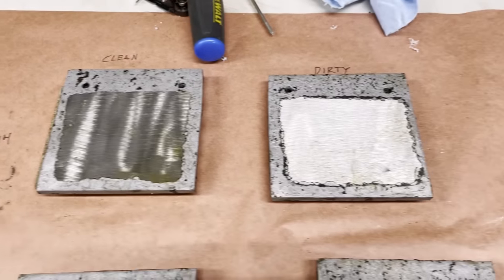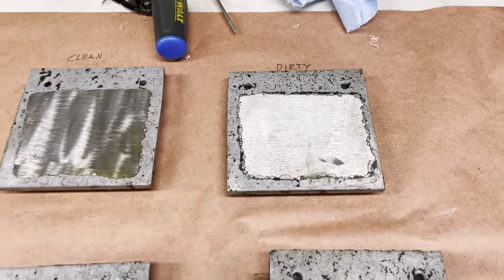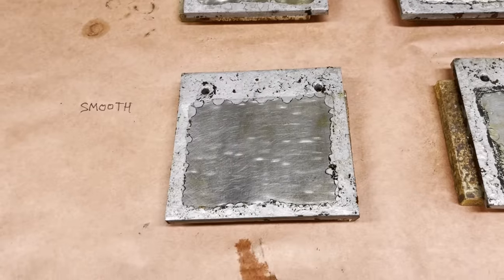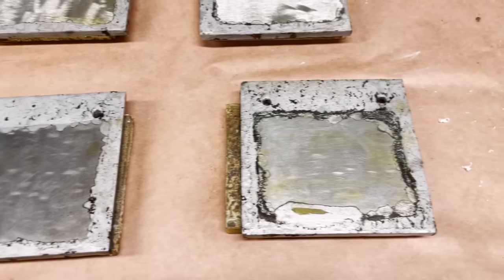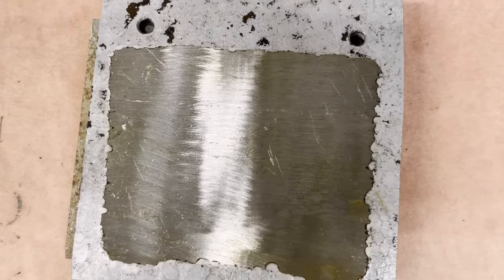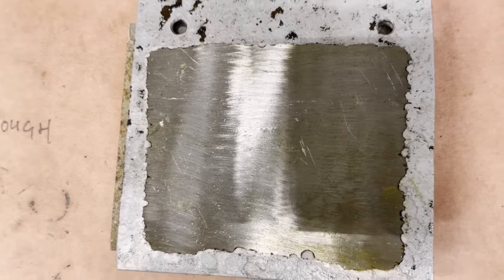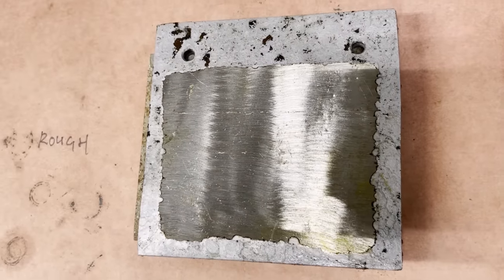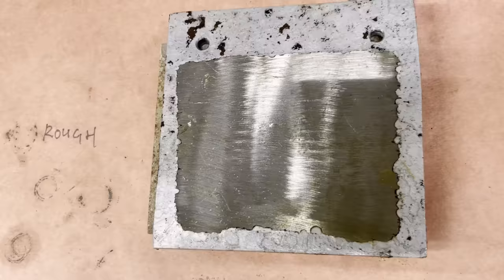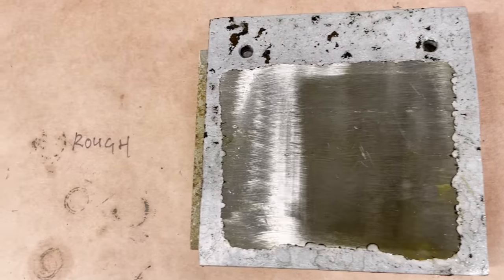At first glance, the coating appears to have protected all the samples against this corrosion stress test, but if you look around the edges, the difference becomes obvious. The rough and clean sample had the least intrusion of rust getting under the edges of the coating, and you can see that nearly the entire coated area is just as it was before the test.